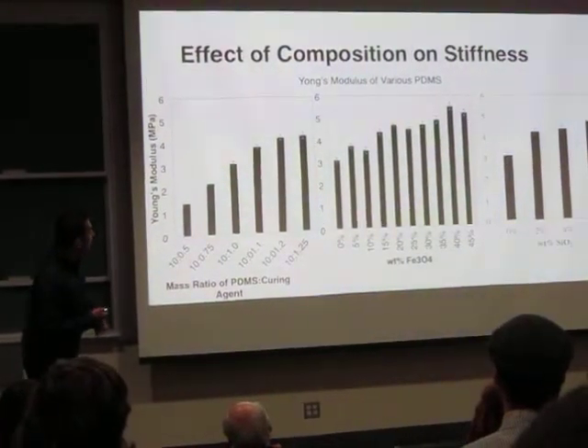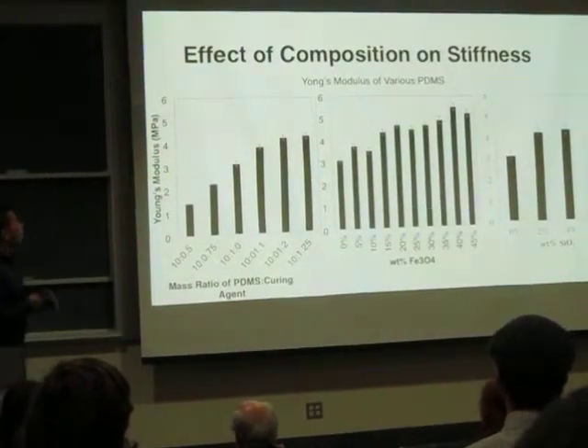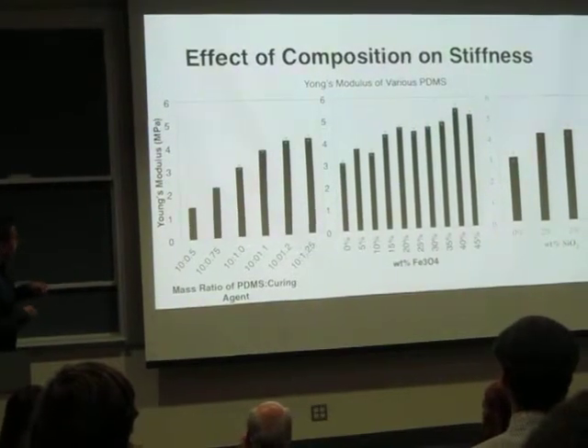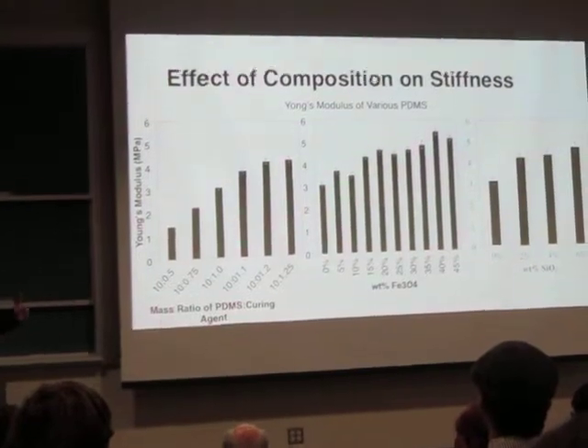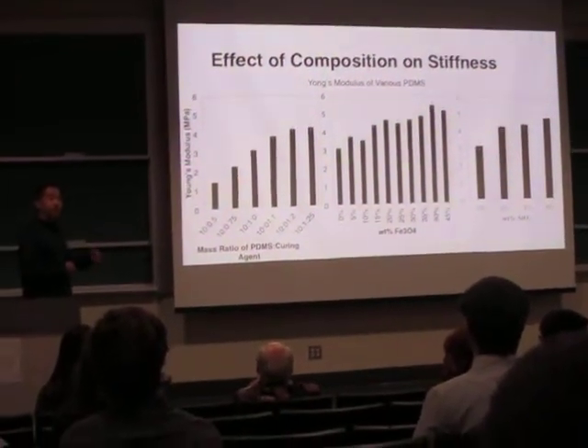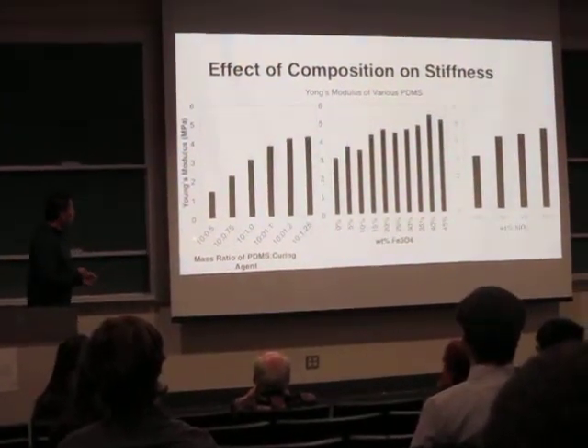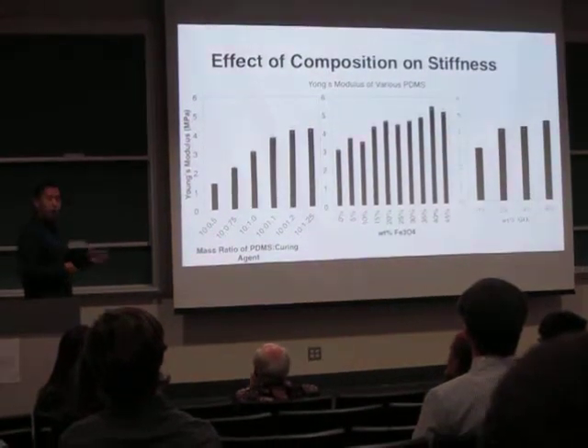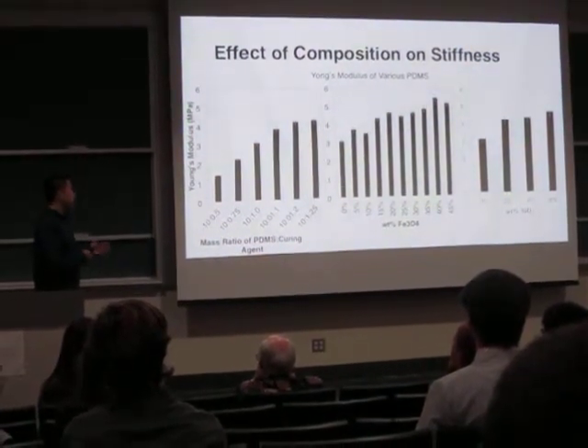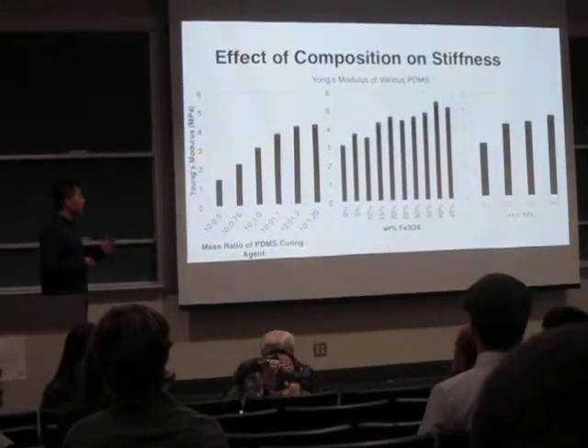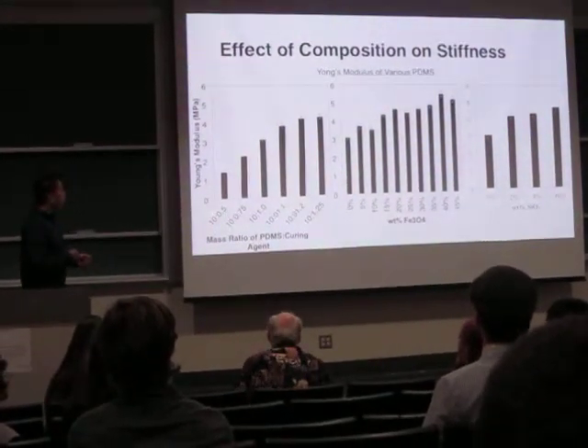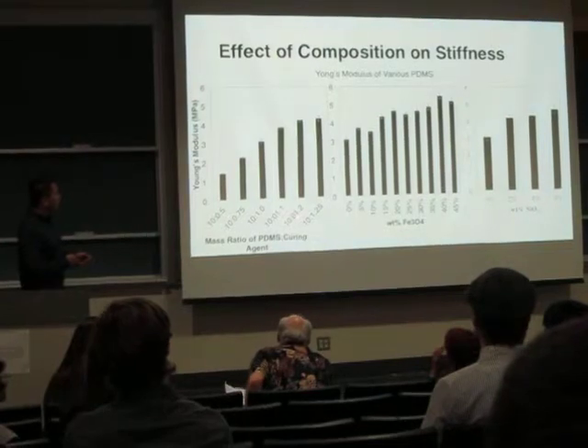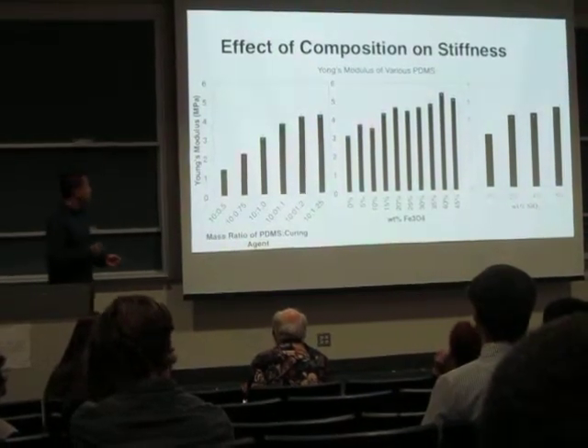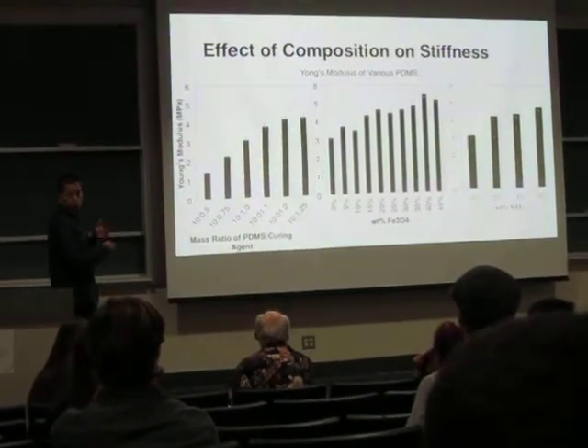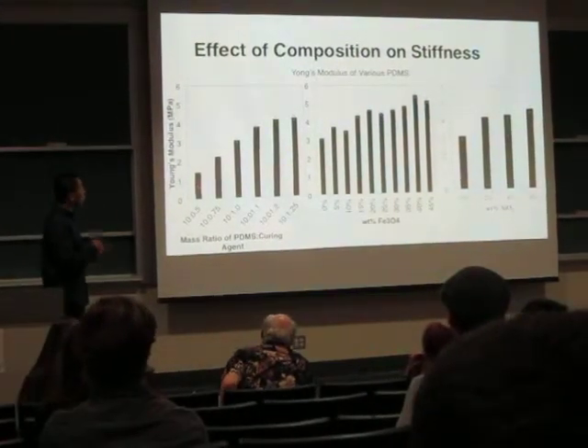And after we did the experiments, the first one is we play with the curing agent. By changing the amount of curing agent, we can vary the strength of the material itself. The first one is a 10 to 0.5 mass ratio, and we keep increasing the mass of curing agent. So we go from 10 to 0.5 all the way to 10 to 1.25. As you can see, the Young's modulus, which is the stiffness, the strength of the material, goes up.